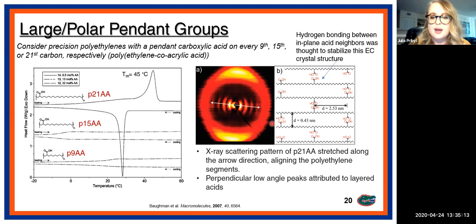So at the time this work was done in 2007, this secondary structure was assigned based on this X-ray scattering pattern. And the reason why this was proposed was because we thought, okay, hydrogen bonding between in-plane neighbors must be stabilizing the crystal structure, because the carboxylic acids are much bigger than a methyl group or a small halogen, but they must be stabilized by the neighbor hydrogen bonding, which is kind of interesting